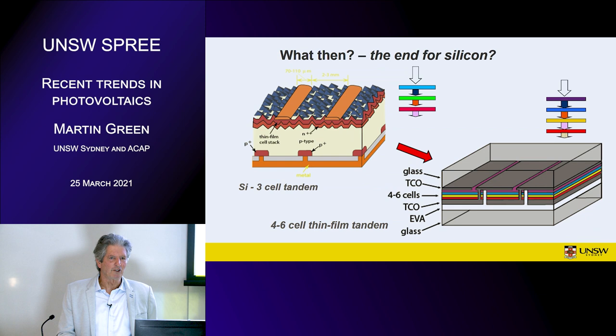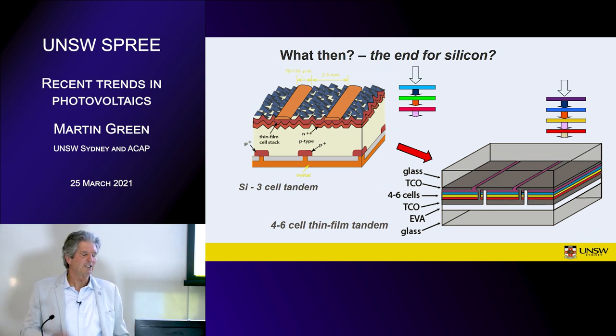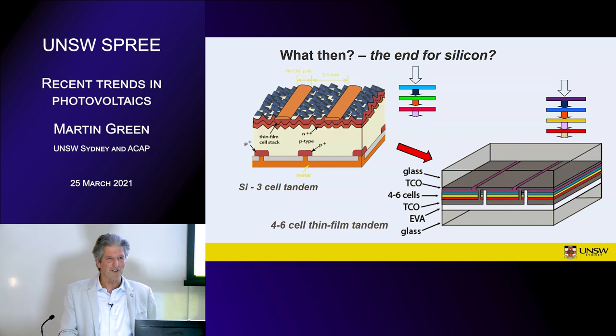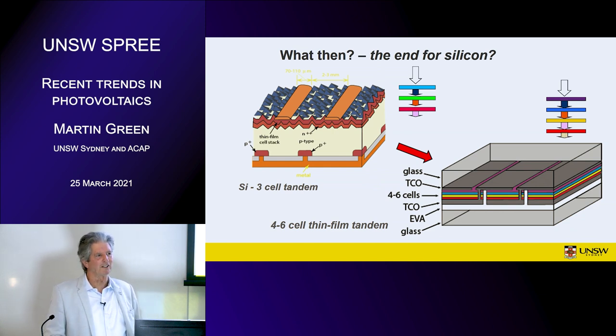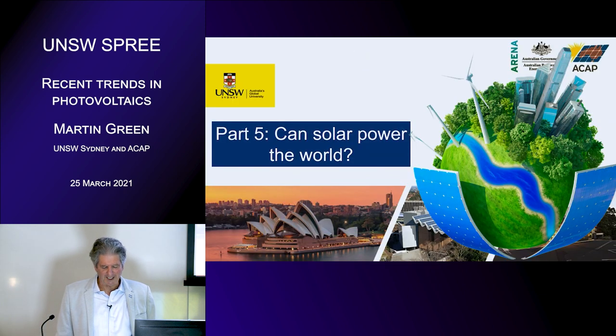But what happens is the silicon contribution to the performance goes down with each cell you stack. So if you stack one cell on silicon, you share the photons. So the silicon only gives half its output power. So if you've got a 24% efficient silicon cell, it'll only give 12% contribution to a two-cell tandem. Three cells only give 8%. Four cells only give 6%. So it's becoming less critical. And by that stage, you'd have enough confidence in these thin film materials that you're stacking onto silicon that you say, well, why do we need silicon anymore? So I think that's my prognosis. If we can get stack cells on silicon to work, we'll transition quickly to an all thin film stack.